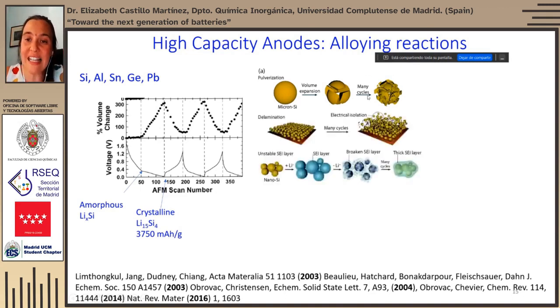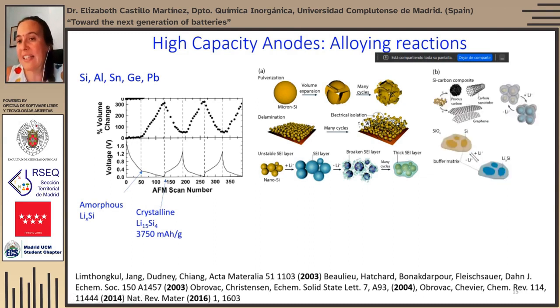Not only does this happen to each individual particle, but also the SEI layer that forms on top of the particles during the decomposition of the electrolyte in the first discharge gets broken. And in the subsequent cycles, a new SEI layer needs to form on the surface of the new particle. Therefore, a very thick SEI layer forms that then prevents proper lithium-ion diffusion.